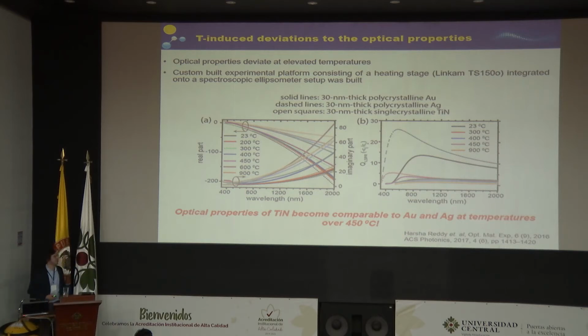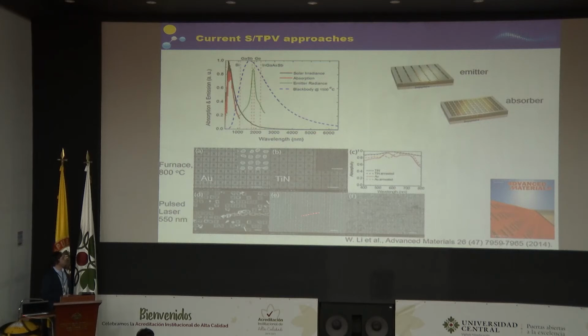So the refractory materials have the same quality of optical properties as the noble metals, which is a strong motivation to use these refractory materials for high temperature applications or in harsh environments above, for example, 400 degrees C. And this is a really astonishing example which was developed in the Shalaev group at Purdue. They developed a metamaterial absorber and emitter for solar thermophotovoltaics, and they tried to heat up the temperature up to 800 degrees C, or use a high amount of energy by pulsed laser.